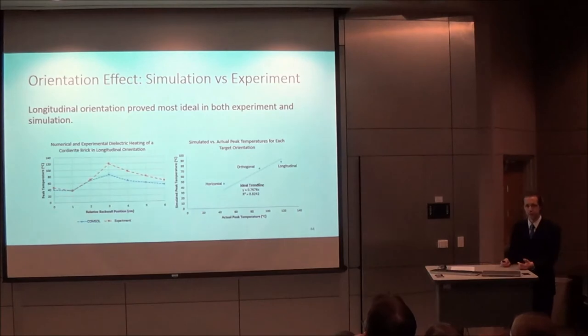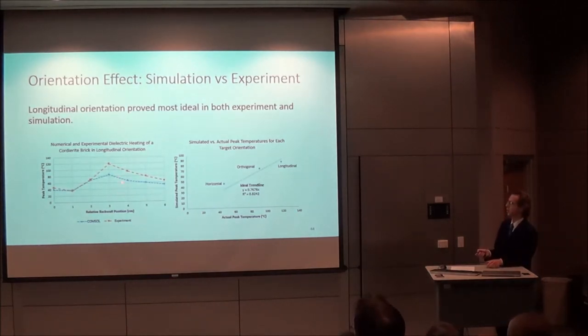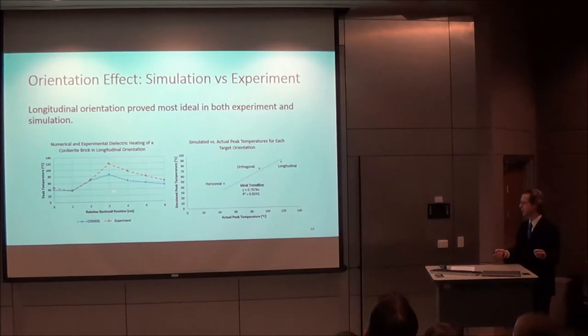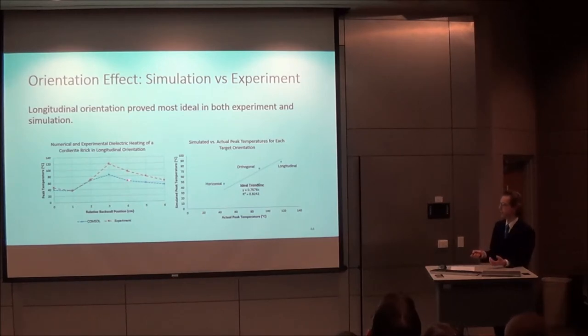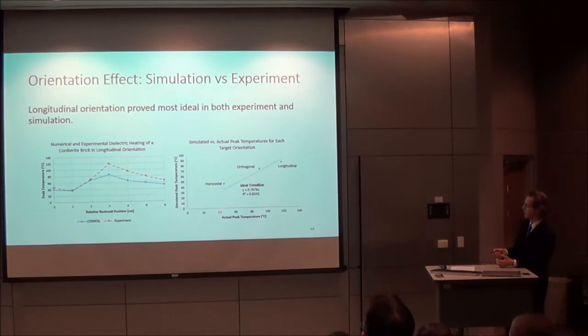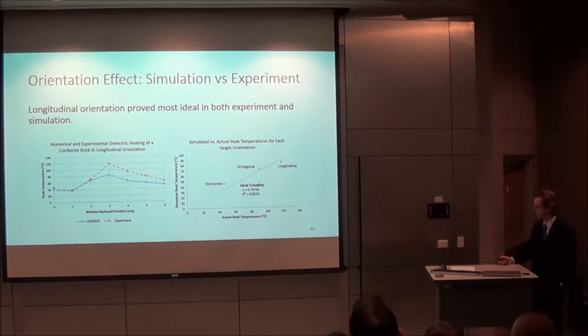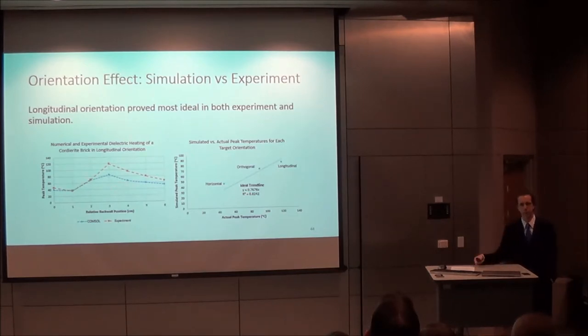This was then compared to the results of the simulation, where we can see that although the magnitude of heating developed in the experiment differs significantly from the prediction in the simulation, the overall shape is similar. So perhaps there's a magnitude offset that is not being accounted for. This is a graph of the simulated versus actual temperatures to compare how well the simulation represents reality. Each of the results for the horizontal, orthogonal, and longitudinal orientations are graphed here. The more linear it is, the better the correlation between simulation and experiment. This isn't an ideal correlation, but it definitely shows that the same trend is being captured by both the simulation and the experiment.